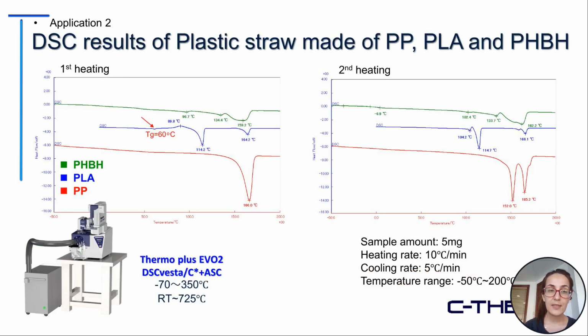Then we look at the DSC results of the plastic straw made from these three kinds of samples, with the first heating scan and the second heating scan. We collected the data from the first heating scan and, as I said, from the second heating scan as well. The green curve again is related to the PHBH, the blue curve is related to the PLA, and the red curve is related to the PP. The samples were heated from minus 50 to 200 degrees Celsius with a heating rate of 10 degrees Celsius per minute and a cooling rate of 5 degrees Celsius per minute, and the amount of sample was 5 milligrams.